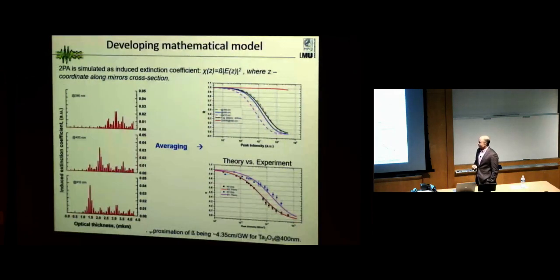Actually, we also made a theoretical model. We just used the two-photon models, and we were able to fit all our measurements very nicely with them. Here is an example, with dots showing the measured curve for reflection versus peak intensity, and with solid lines the theoretical calculation, including that our material has two-photon absorption. By this we can also define our nonlinearity parameters for the materials.